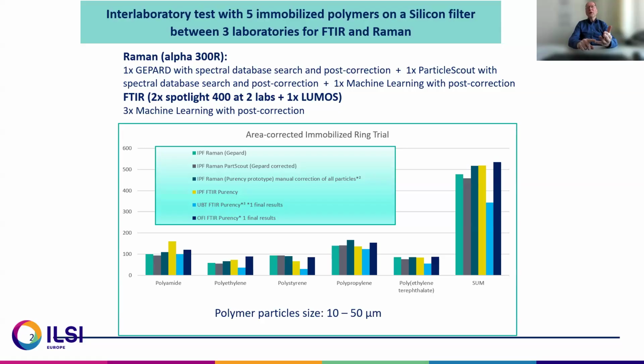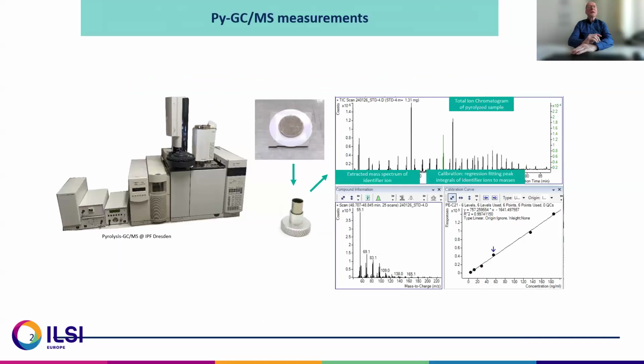What you see at first view is that the light blue has too low values. And what we learned from this was that this laboratory was the only laboratory which used Anodisc. All others used silicon filters. So if you use a machine learning approach, you also have to teach the filter material to the evaluation.